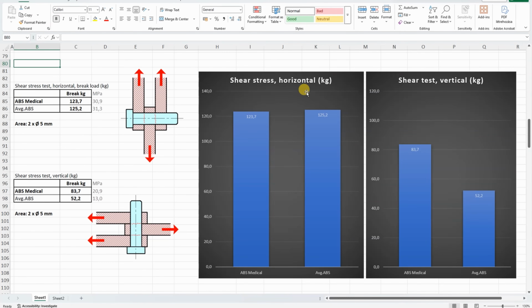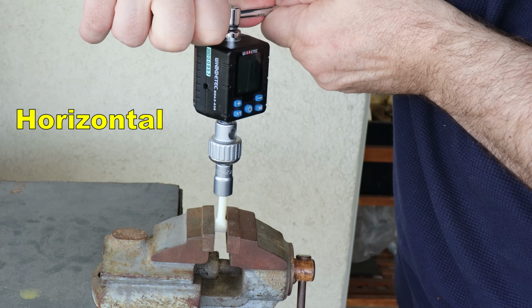Printed in horizontal position, very similar value compared to average ABS. Printed in vertical position, the layer adhesion is important, and here we can see big improvement compared to the average ABS material. Torsion test, horizontally printed.